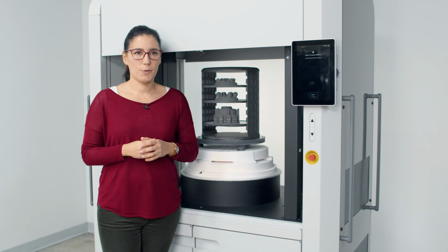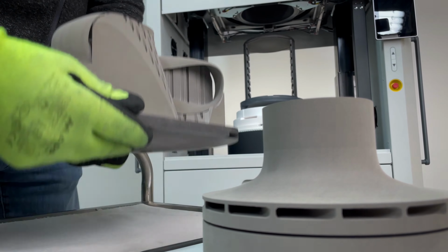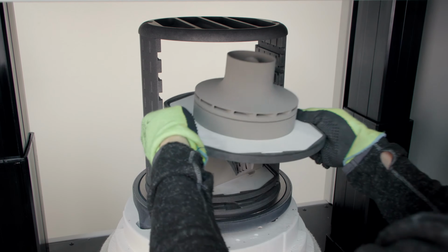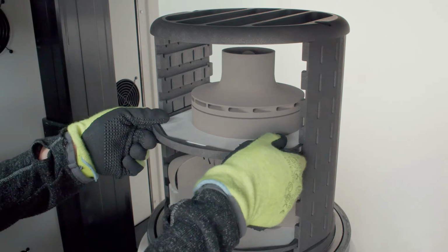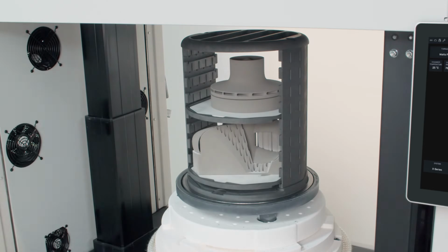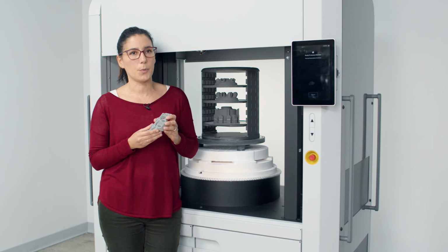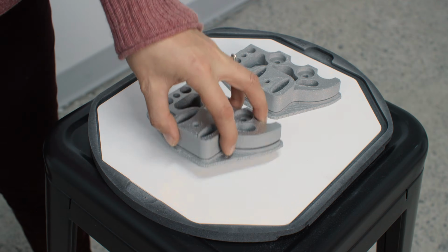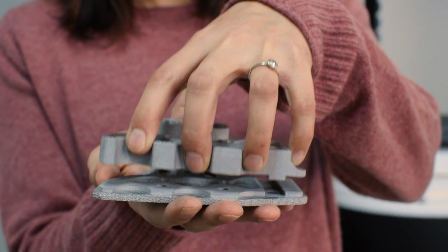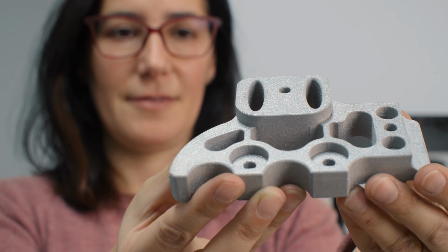With PureSinter, we've shown that with intelligent furnace design, we can sinter titanium cleanly to high density with mechanical properties meeting and exceeding ASTM standards for post-sinter hipped titanium materials, which means that you can get the properties right out of the furnace without needing to densify it post-sinter through hipping.